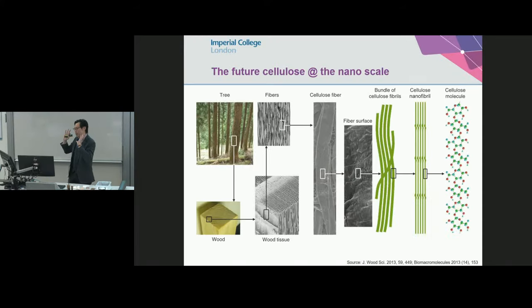I've shown you this slide earlier. You have wood, you remove lignin, you end up with these cellulose fibers down here, which you actually use to make paper. You find ways to dissolve it into a molecular structure. You spin textile clothing, so you wear them. So cellulose is great on that. At this level, you can actually make your Gordon Aerolite, those composite structures that I presented to you earlier. But wood itself is, mechanically speaking, 5 gigapascal in compression modulus, 70 megapascal in strength. So that's just slightly better than some of the polymers that you experience every day.